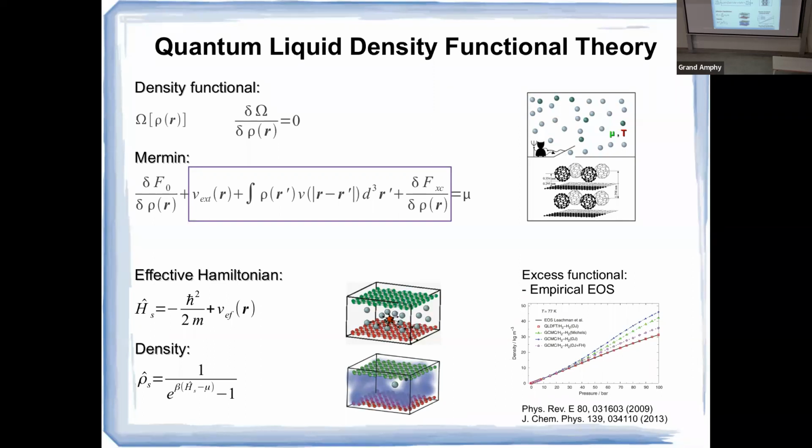Let me note in passing that this is different from the standard liquid DFT calculations, in the sense that usually in liquid DFT, the one used for atomic or molecular fluids, most authors try to model this term, writing it in an explicit form, with explicit dependence on the density. But here we are following more a Kohn-Sham-like scheme, treating the kinetic energy effects exactly by setting up the Hamiltonian for this effective reference fluid moving on the effective potential energy surface.